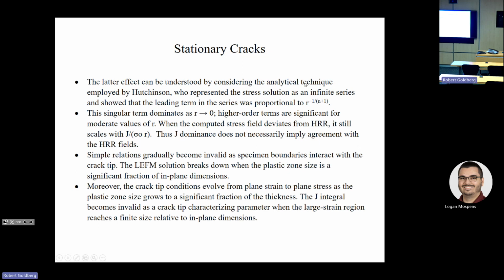So if we go back to the methods that were employed by Hutchinson, he took the stress, defined it as an infinite series, and showed that the leading term was proportional to the radius to the -1 over n plus 1. And as r gets closer to 0, the singular term dominates, and higher order terms are only significant for moderate values of r. So when the computed stress field deviates from HRR, it still scales with J divided by sigma naught times r. So J dominance doesn't necessarily imply agreement with the HRR fields. And simple relationships also become invalid as your specimen boundaries interact with the crack tip.